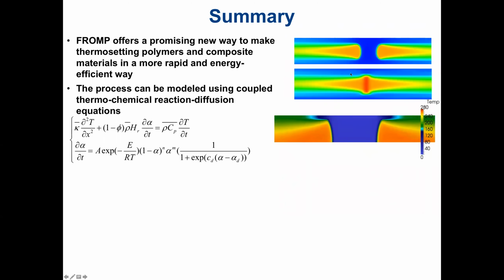So on the right, you can see an animation that was done for the interaction between two fronts. The top two figures correspond to an experiment where two fronts were started from the left and the right and joined in the middle. We know that as the fronts merge, the heat has nowhere to go. So we observe and predict a thermal spike. And we're looking at ways to alleviate this particular effect.